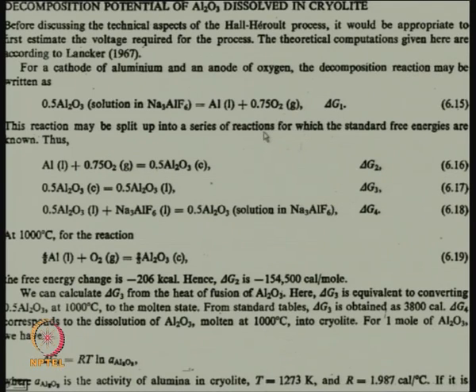The reaction may be split into a series of reactions, and this you must understand. Firstly, consider pure alumina. The formation reaction is 1 aluminum plus 0.75 oxygen giving 0.5 Al2O3, the C meaning solid. Now, assume that this solid alumina becomes liquid alumina, and that liquid alumina dissolves in liquid cryolite to produce alumina in solution in cryolite.